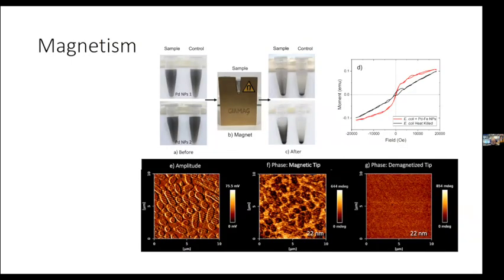This is not the same strain, but just to show you briefly that also this magnetic concept works. On the top, you see why we're working with BioMAG here, because the company produces these very massively strong static magnets. What we can do is use our E. coli suspensions that have produced nanoparticles and just check if the particles are being pulled towards the sides of the tubes, suggesting that the particles are indeed magnetic. On the top right in this picture, you see that there is actually a magnetic moment to this that we can measure. At the bottom, we show magnetic force microscopy to show that where the contrast is is the magnetism and that this is directly where the cells are. This is not happening outside of the cells, this is really directly related to what's inside the cells.